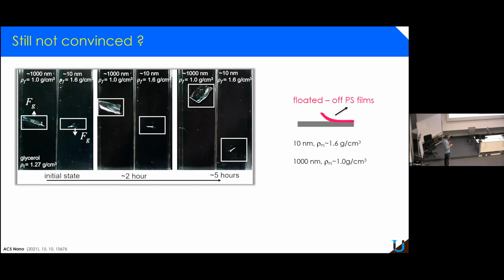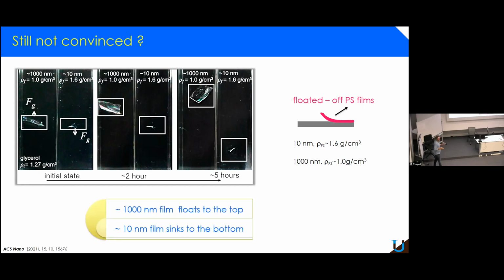He simply spin-coated the film, floated it off, and put it in a glycerol liquid. Glycerol has a density of 1.25. He made thick and thin films, and he left the system for many hours. And at the end, the thin film was going down, and the thick film was staying up. So for me, it's direct proof that the 2 films have different density, and that the thin film has a density that is higher than the glycerol.